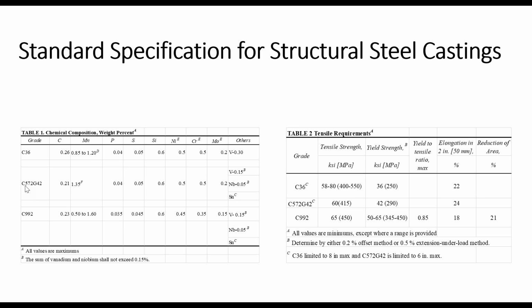We do the same thing for C572, which is ASTM A572, grade 42, which means it's got a 42 KSI yield strength minimum. And we have exactly the same composition. We do bump the silicon up a little bit, but it's got the same composition and the same properties. And then the ASTM A992, we call C992, it has the same composition. And you can see that for both of these grades, to make sure that you can meet the properties, it's permitted to add vanadium or niobium in order to get the requirement up. And so you can see that we really can make the mill grades as cast grades if we get this.